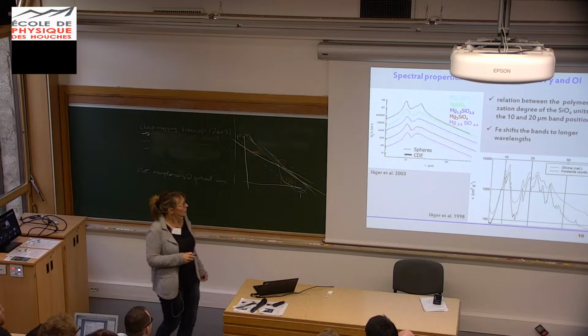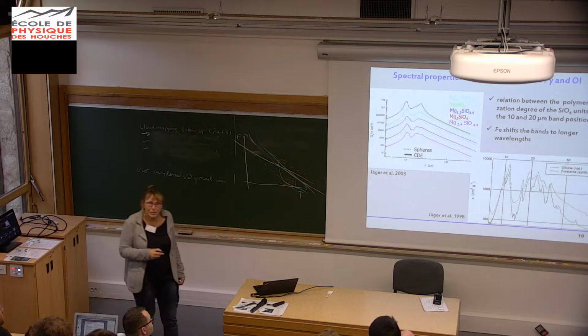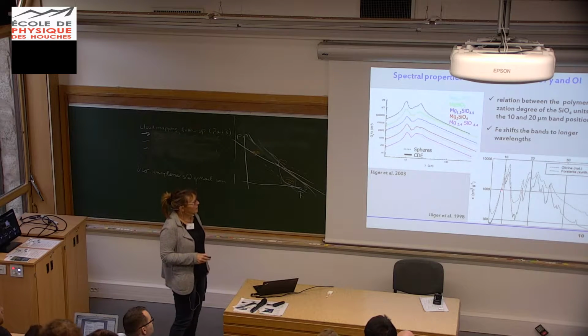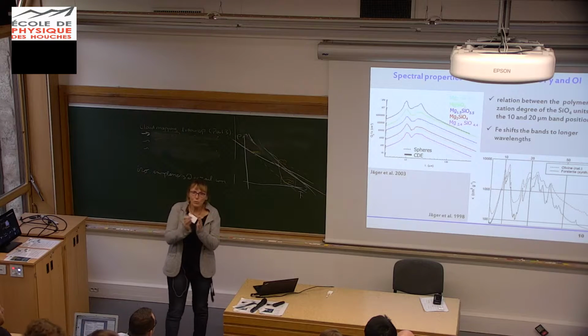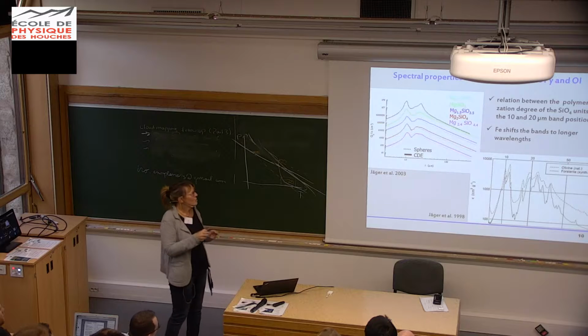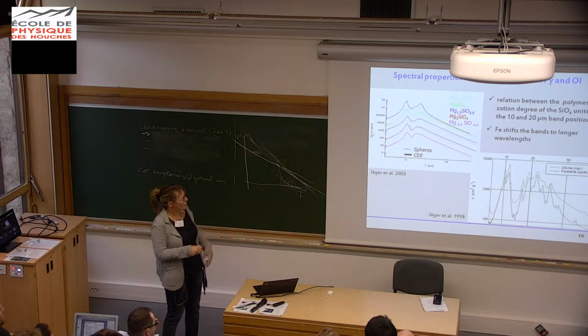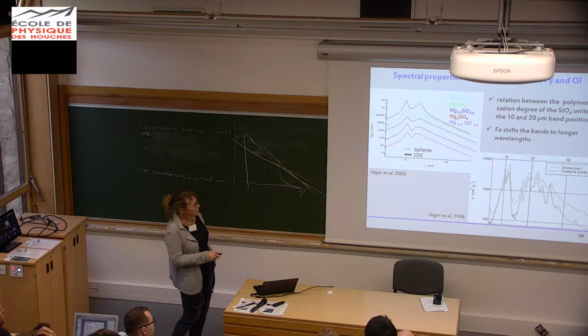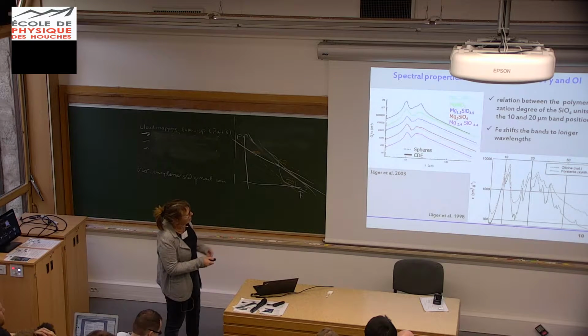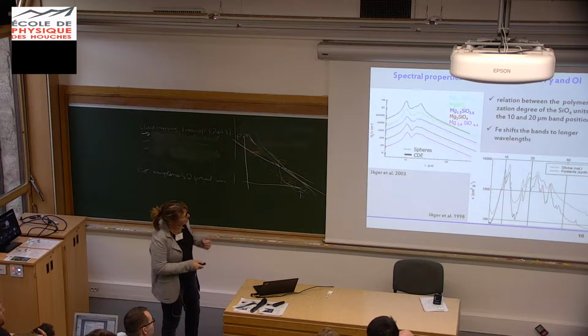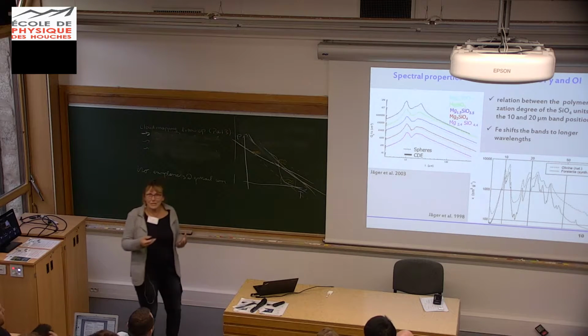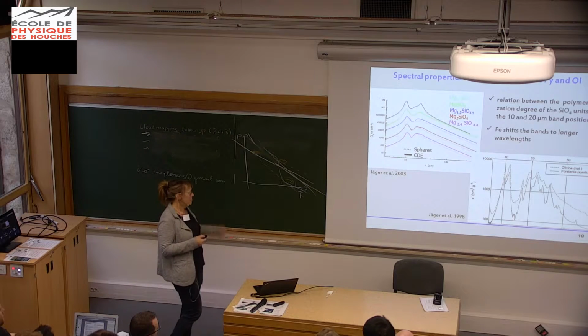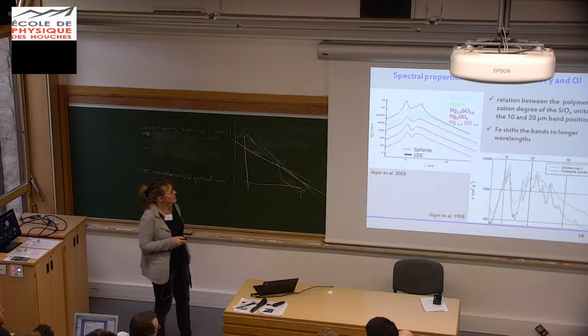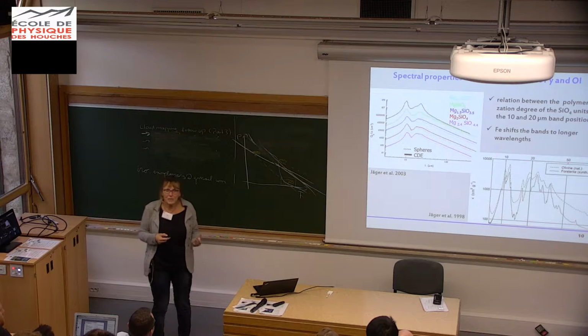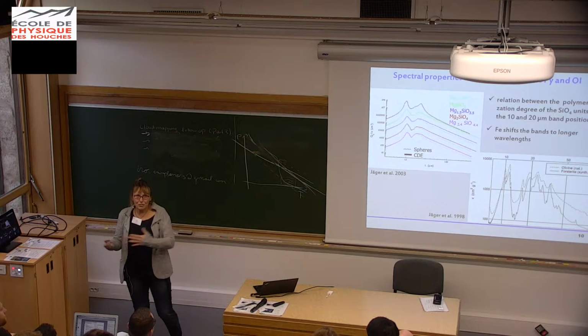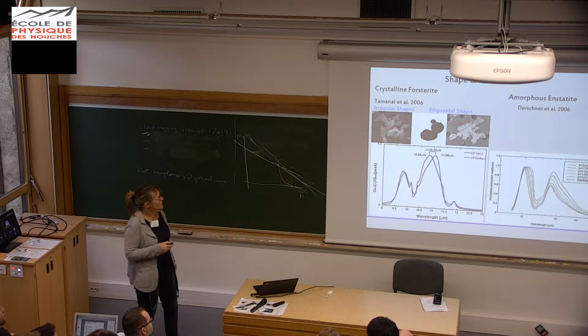However, this is not so clear - this is a very clear trend only if you look at the magnesium silicates. If you introduce iron, you get a longer distance between the metal and the oxygen, and this also shifts the bands a little bit to longer wavelengths. This is well seen in crystalline material because we have narrow bands, so we can more clearly see the shifts. But this is of course also a tendency you would see in amorphous material. So you have to keep in mind that the polymerization degree, and also the introduction of iron, may shift the bands, and of course also shape effects.